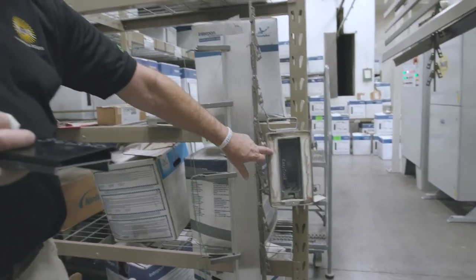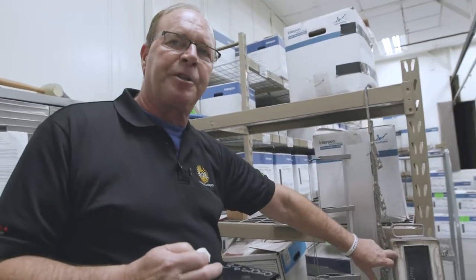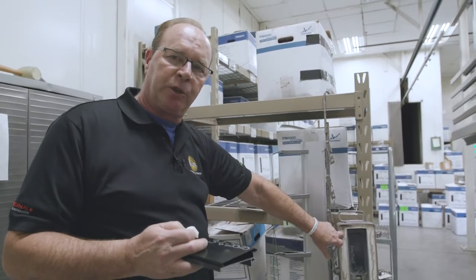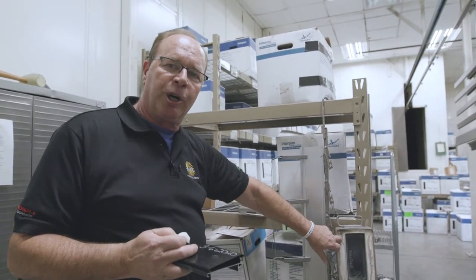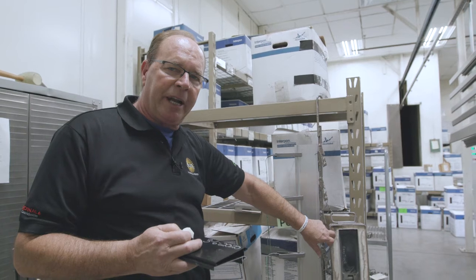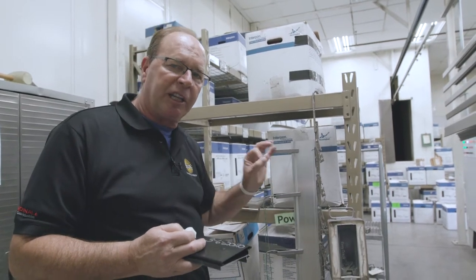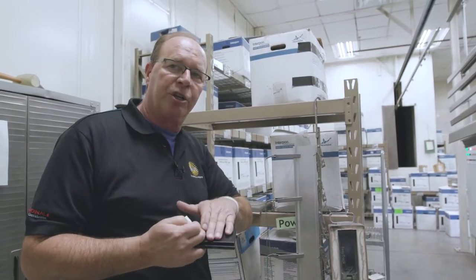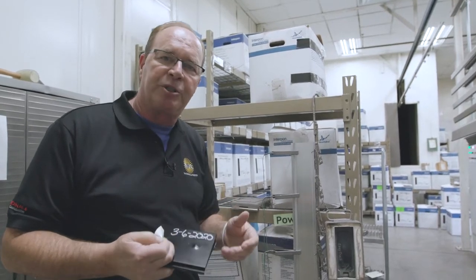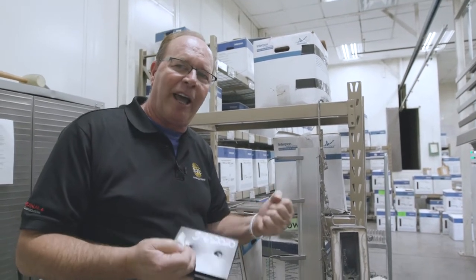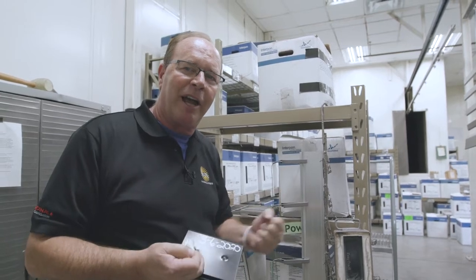In addition to this documentation, we run what's called a data pack through the line over here, and this is also run through twice a day, which monitors the line speed, which is 3 feet a minute, and also the curing oven, which is 28 minutes at 400 degrees to get the perfect recipe to make sure the powder coating on our aluminum extrusions is going to be long lasting and super durable for the lifetime of the product.